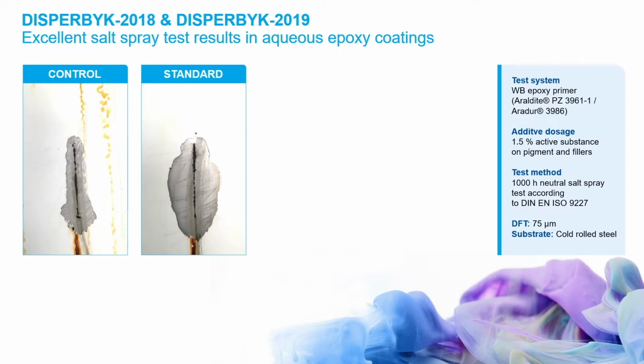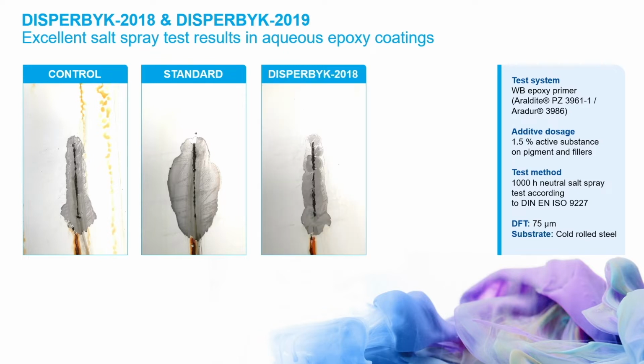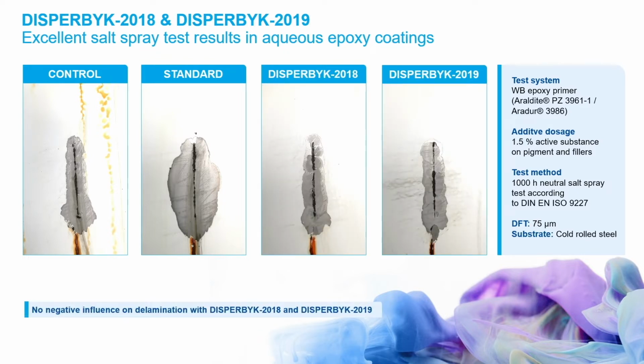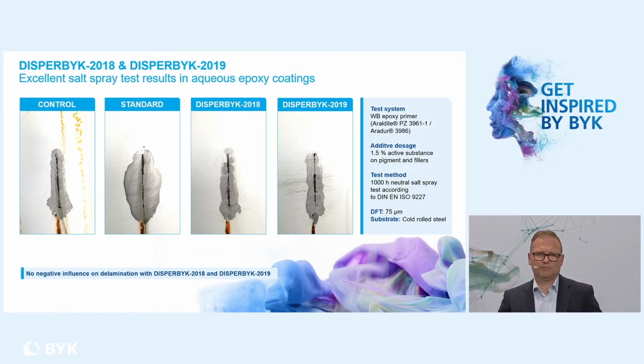Co-grinds. Now we are coming to marine protective. Here, an example, water-based epoxy primer. We use titanium dioxide and fillers, and we add 1.5% active on the fillers and pigments. And here, with a standard, first you see something is going wrong there. There is a loss of coating properties, especially delamination occurs. And with DISPERBYK 2018 and 2019, it's really minimized. We achieved this by a very good balance between the hydrophobic backbone on one hand and the hydrophilic side chains, which you need for the stabilization of the pigments. But because of the good balance between these two, let's say, chemical chains, we minimize the side effect of corrosion.